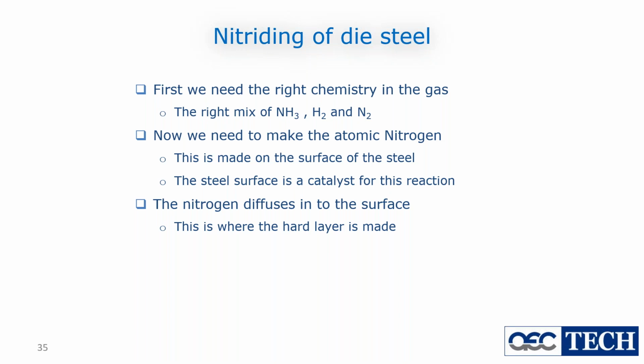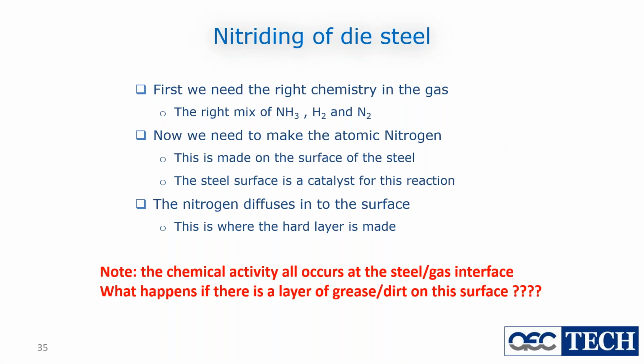And we need to make the atomic nitrogen. This is made on the surface of the steel, as Richard said, not in the environment. The steel surface is a catalyst for this reaction. The nitrogen diffuses into the surface. This is where the hard layer is made. But we don't need a very thick hard layer because it also makes it brittle. The chemical activity all occurs at the steel-gas interface. So what happens if there's a layer of grease or dirt on the surface? I think Richard is going to show us in the next slide. Yeah.